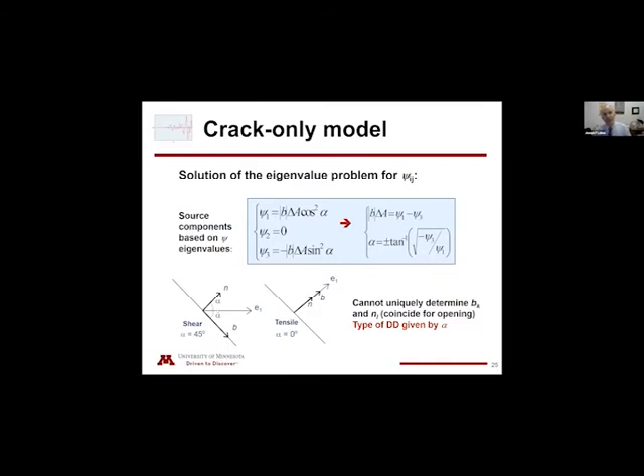So the mechanism will only be known if this angle is 0 because then N and B coincide. So the important information that we'll be able to obtain from this analysis will be B, delta A, alpha, from which we will be able to compute N and B, but N and B can be interchanged.